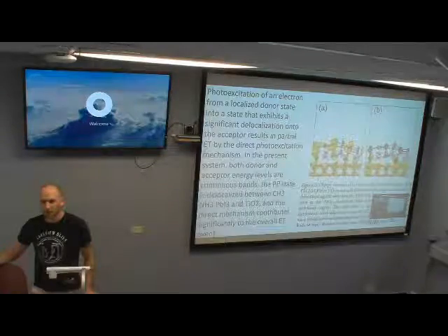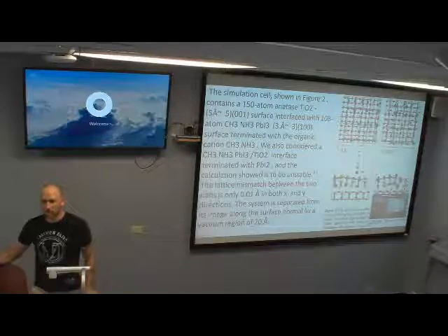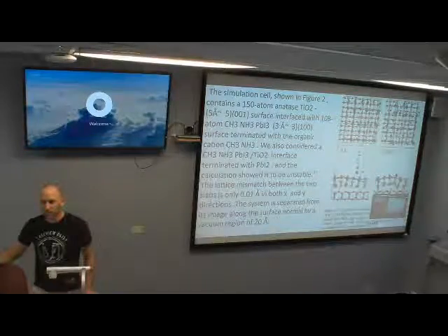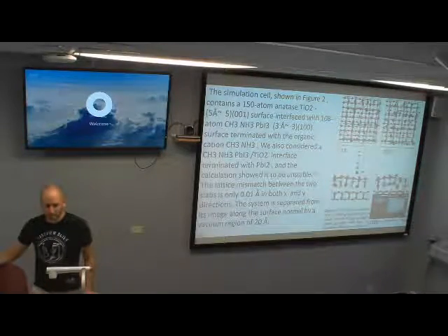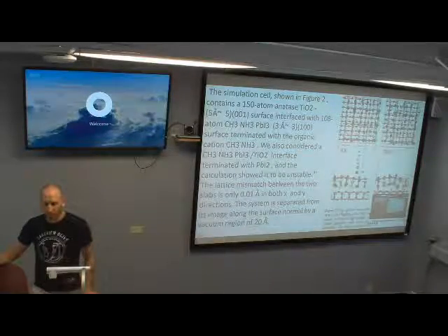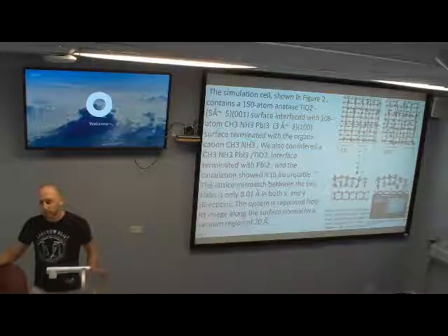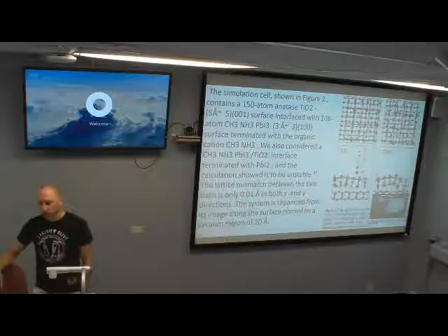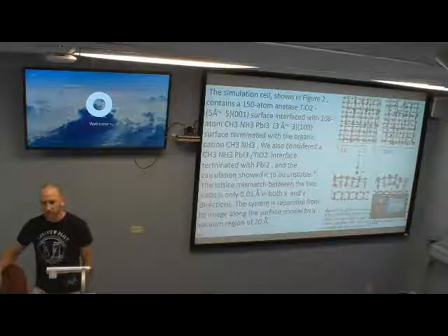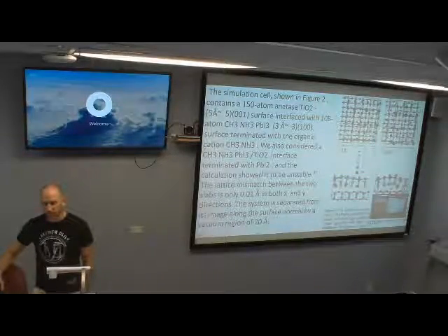Yeah. Also two layers. And then they have a vacuum. So technically they have a huge confinement along the Z direction, right? What is a two-layer size? It's probably less than 1 nanometer. The typical size of the unit cell in perovskite is like 6 angstrom, so it's less than 1 nanometer. And for titanium, two layers, just looking at the figure, it's also less than 1 nanometer.